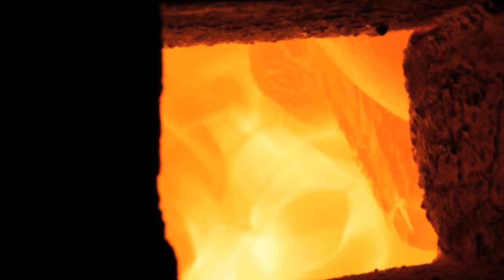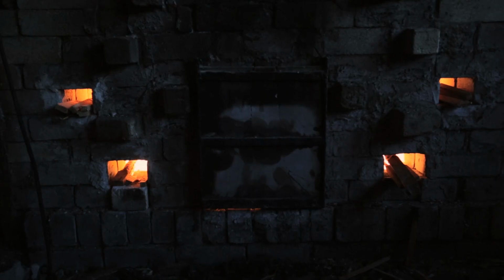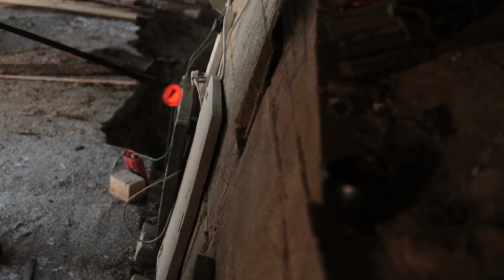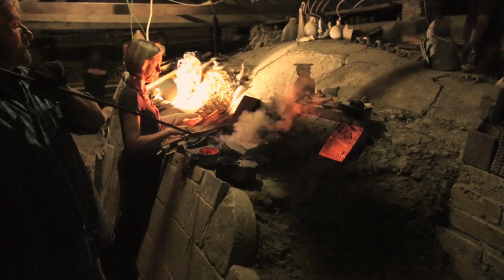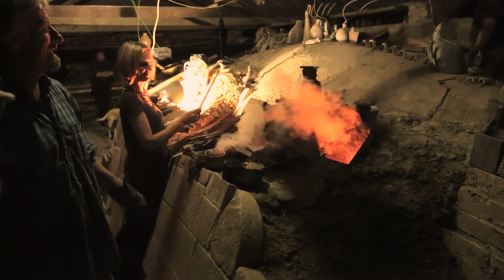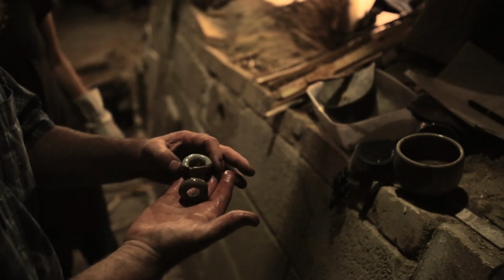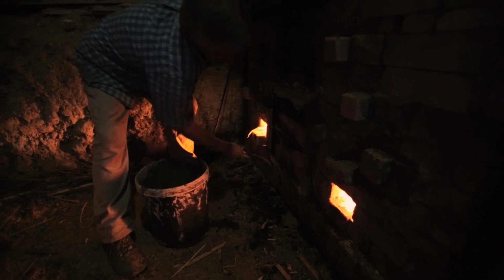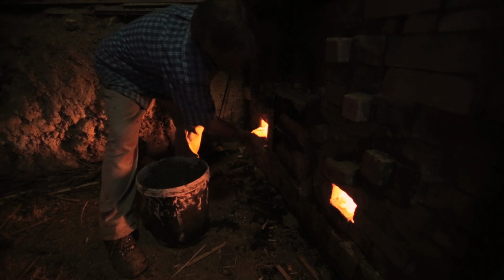We then soak for about 8 to 10 hours. At that stage, we've got indicators inside the spy holes and rings of clay which we can draw out of the kiln to actually see what the glaze is doing. It's then time to stop stoking and let the kiln cool quite quickly down to 800 degrees. Then it's all sealed up and left essentially for about 3 days.